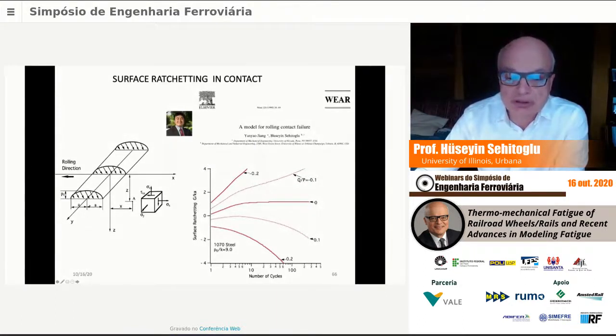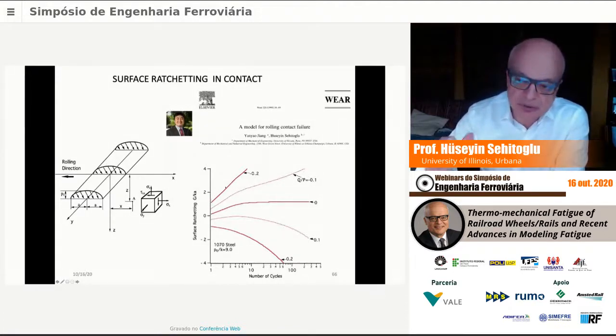So the surface ratcheting, this is normalized, multiplied by the shear modulus, normalized by the yield stress and shear, times half the contact patch here, that's used here, number of cycles here. So we have clearly a model that predicts the ratcheting. So this is Q over P zero means pure rolling, no shear tractions. And Q over P equals, well, minus 0.1, 0.1. This is the difference between driving and driven.